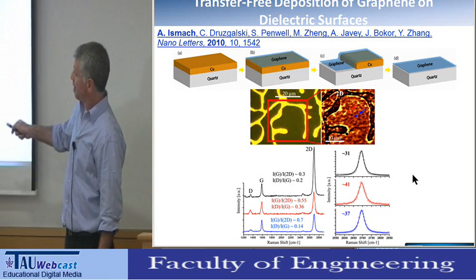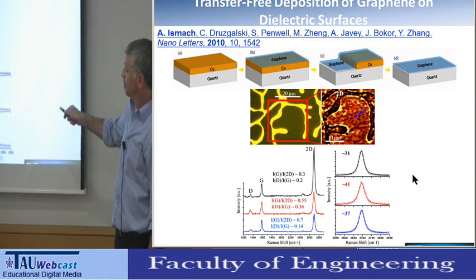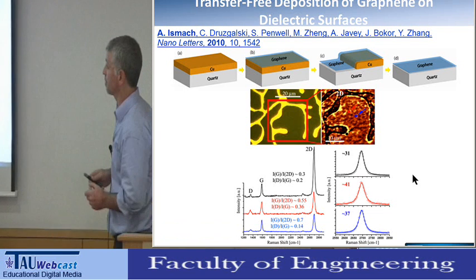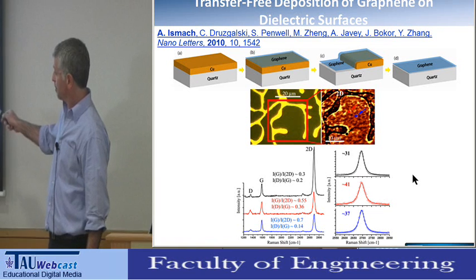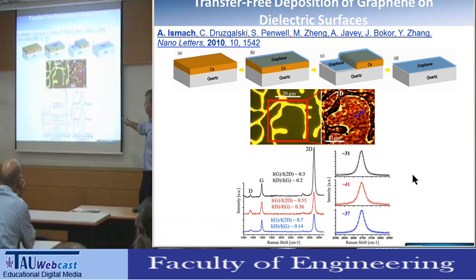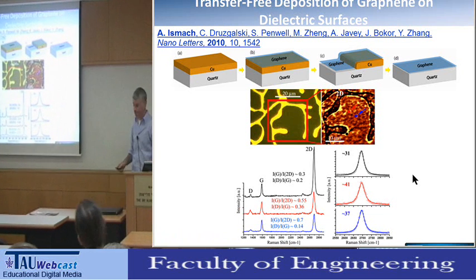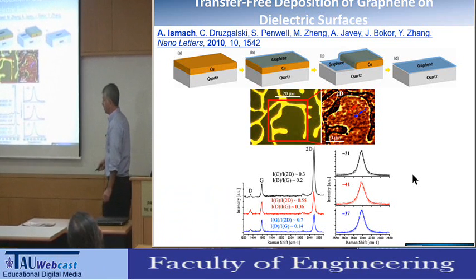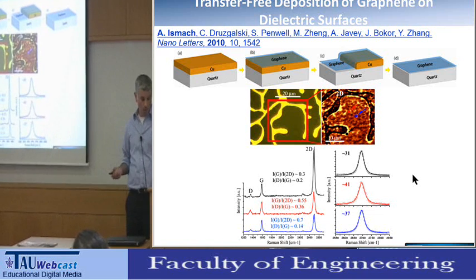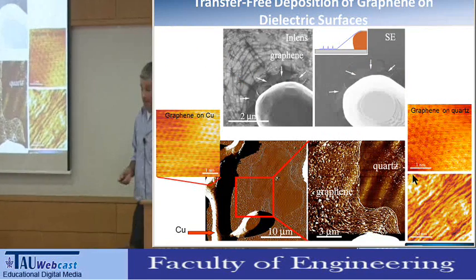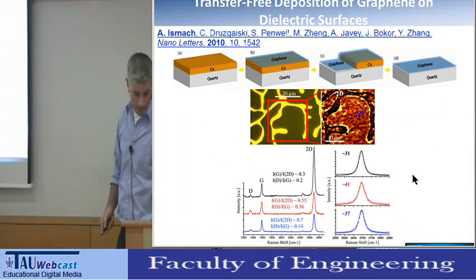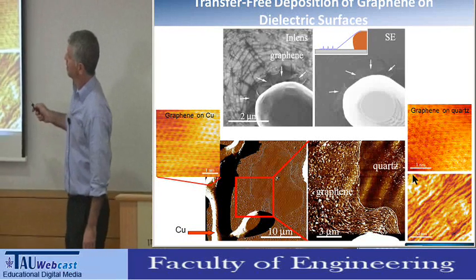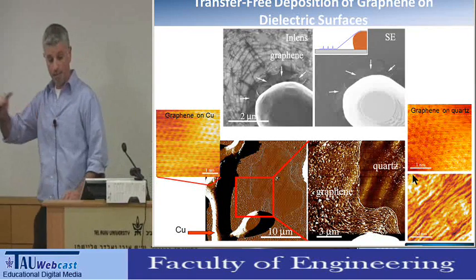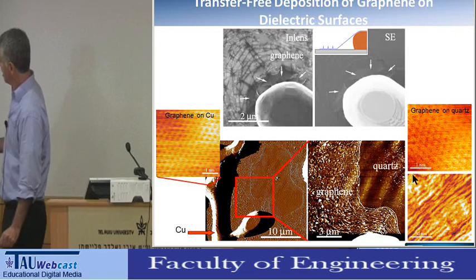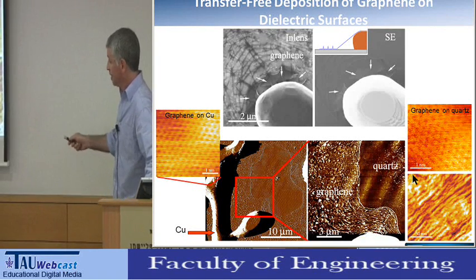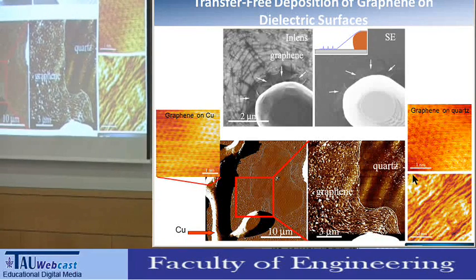So here is an optical microscope image of the wetting of the metal, showing a different finger structure, which is very common in the wetting of metals on surfaces. But in between the metal, you can see by Raman mapping, in this case of the 2D peak, that the area is fully covered with graphene. And by analyzing the graphene again, you can say that it is mostly single layer graphene. The reason that you are seeing a small D peak here is that the deposition of the graphene is not smooth, and the graphene on the surface appears to have a series of wrinkles that are parallel to the metallic structures, and these wrinkles are in the micron scale, but also in the nanoscale. This is AFM and this is STM.